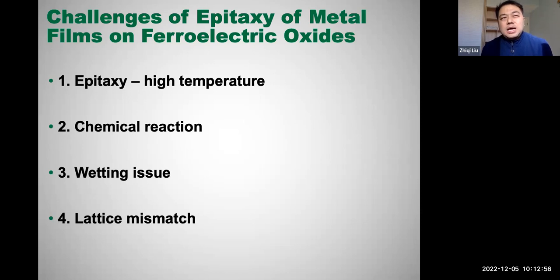And the other important issue is the wetting issue, because the surface energies of the metals and the oxides are naturally different. It's like when you make a droplet of water on top of a piece of glass, there will be a wetting angle. So the metal films, especially at high temperatures, could not lay flat on the surface of oxides. That's also a big problem.